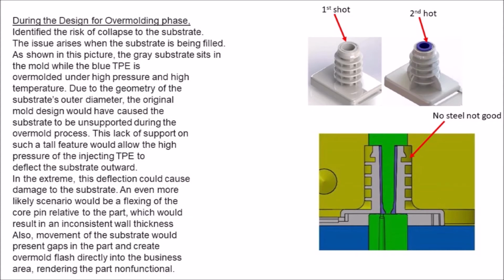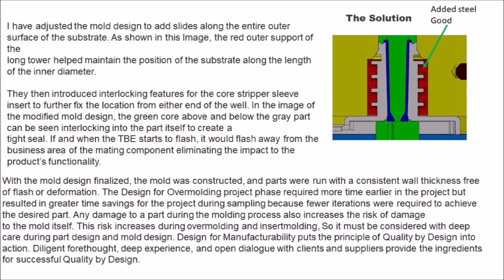An even more likely scenario would be a flexing of the core pin relative to the part, which would result in an inconsistent wall thickness. Also, movement of the substrate would present gaps in the part and create overmold flash directly into the business area, rendering the part non-functional. I have adjusted the mold design to add slides along the entire outer surface of the substrate. As shown in this image, the red outer support of the long tower helped maintain the position of the substrate along the length of the inner diameter.